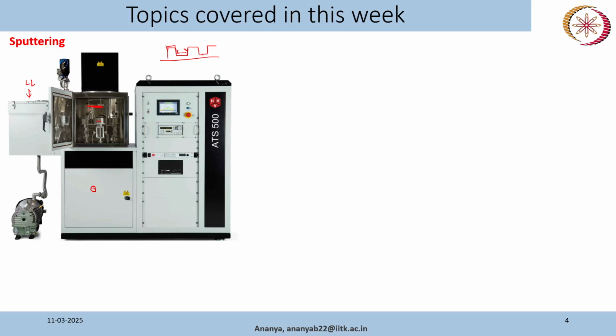So there will be two shutters in this kind of system. One is at the top of your target, and one is at the top of your substrate. Say you create your plasma and the sputtering is actually happening, but you are keeping both the shutters closed. Then the top layer of your target will be sputtered onto the shutter, the side walls, or anywhere, but not directly on your substrate. We normally do this process for say 20-25 minutes, and after that we open the shutter to get the actual deposition on our substrate. That is why we can get a good quality film using sputtering.